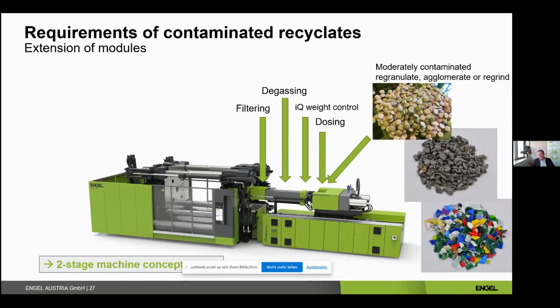And if we run such materials, or materials like the agglomerate or a different recycling material, then some additional systems should be installed on an injection molding machine. This can be either a dosing for the feeding and hungry feeding of the system, because due to this there is a certain opportunity to have backwards venting and also to have always the proper portion in the screw. The IQ systems, weight control, it's obvious, and two further systems should be implemented on the injection molding machine, which means the degassing and the filtering on the system.